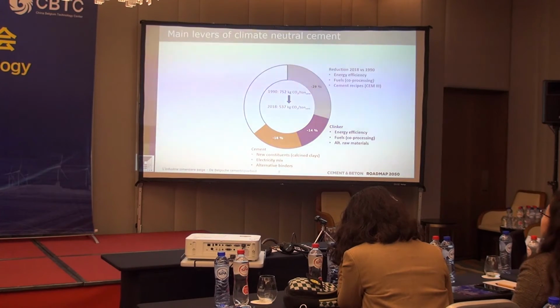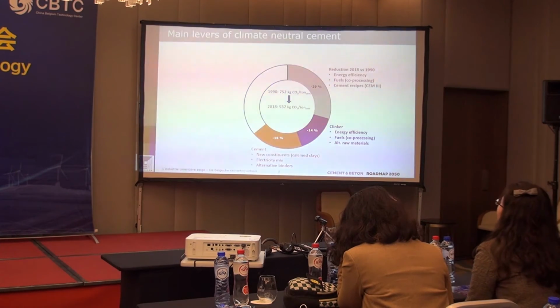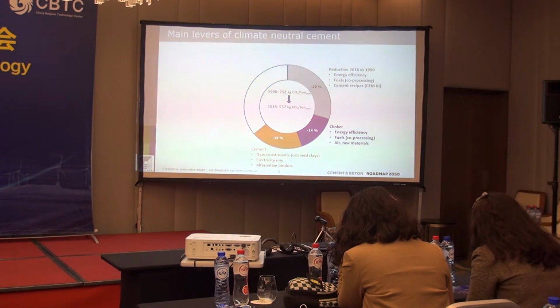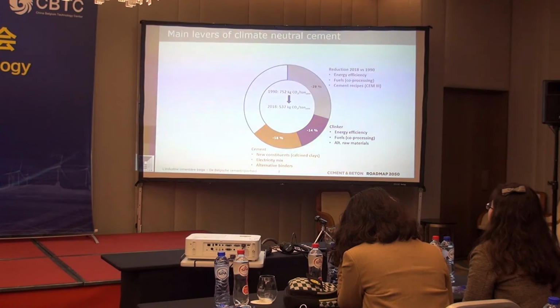In Belgium, we absolutely have to do it because today we use a lot of steel blast furnace slags. But this blast furnace slag will disappear someday because the steel sector is also busy with its roadmap and developing new processes like direct reduction of iron ore. So they will no longer produce this waste, and we will not be able to use it for cement production. And also what we call the alternative binders, like the alkali activated materials. These are also directions of research. We are not convinced that 100% of the market will use these materials, but there are some possibilities, and once again we go back to this idea: the right material at the right place for the right application.